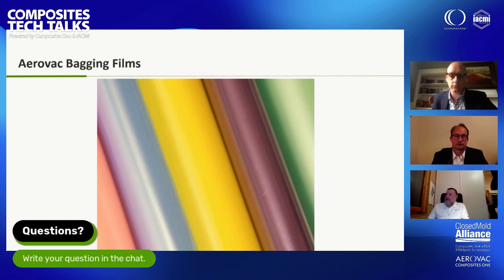In wind infusion, typically we supply 3 different grades of multi-layer film. We've got the Vacuum 400 yellow, Vacuum 465B, and Vacuum 850G. These are identified by different colors, yellow, blue, and green, mainly supplied in 75 micron thickness, even if other thicknesses are available and can be made, with different performances as per elongation and maximum application temperature. So to match the different working and environmental conditions on the market.